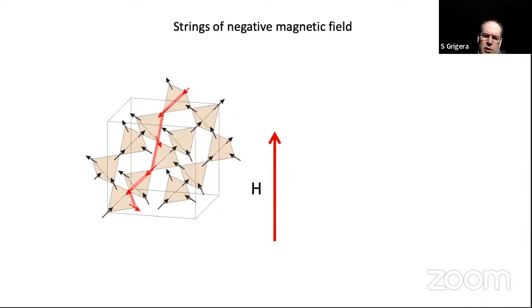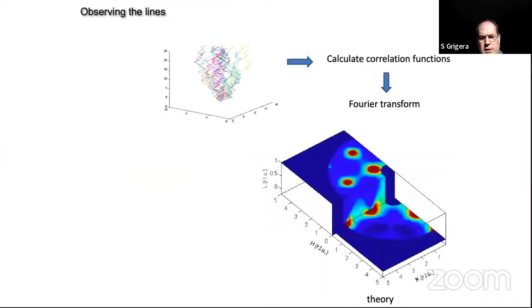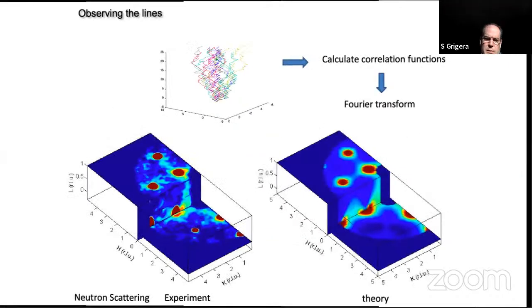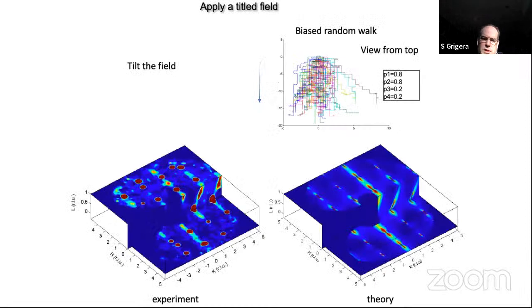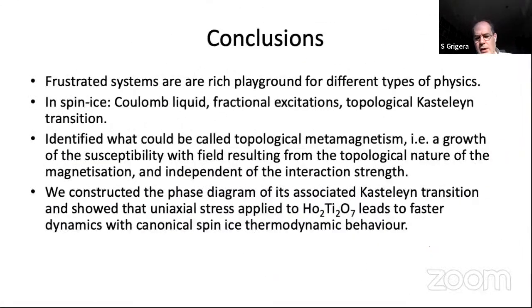So our plan is to explore these dynamics as a function of uniaxial tension. I won't show you this. This was just a confirmation using neutron experiments. If you want to confirm that the excitations look like lines, you can do a neutron experiment adding the magnetic field. And here what we did was to put a tilted field so that you have a biased random walk, and then you compare the correlations of a biased random walk with the correlations you measure with neutron experiment, and you see again that this description of the excitations of the system in terms of strings is a good description.